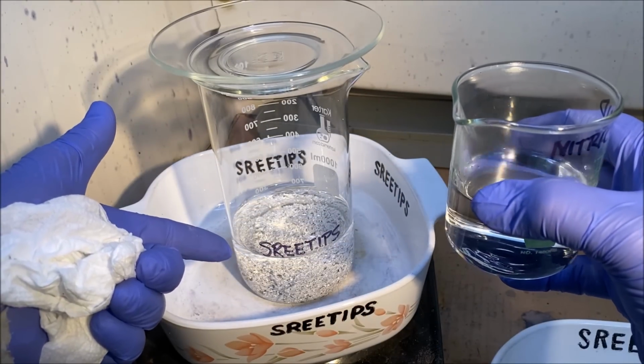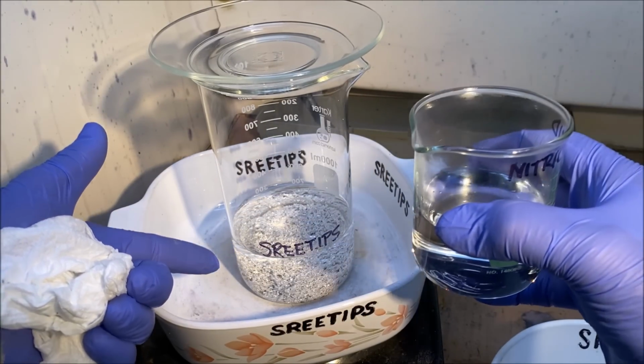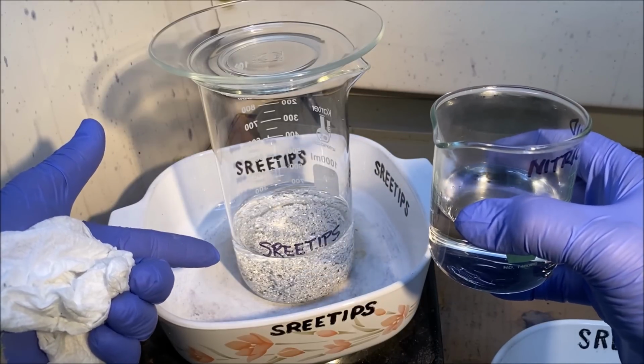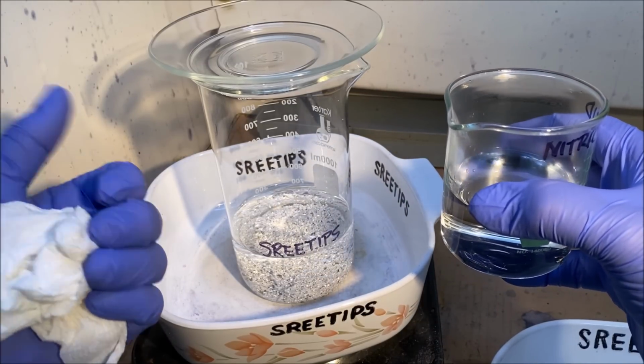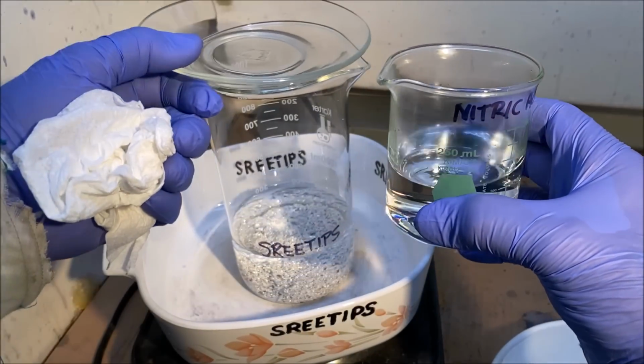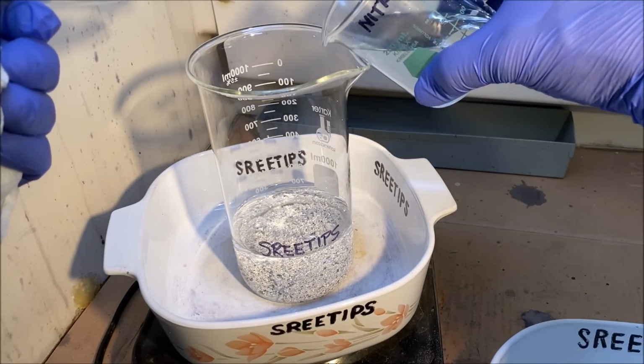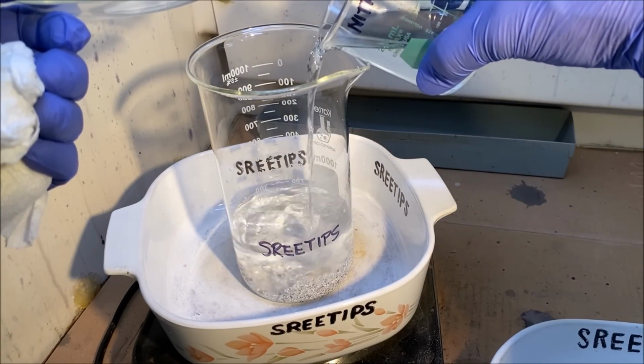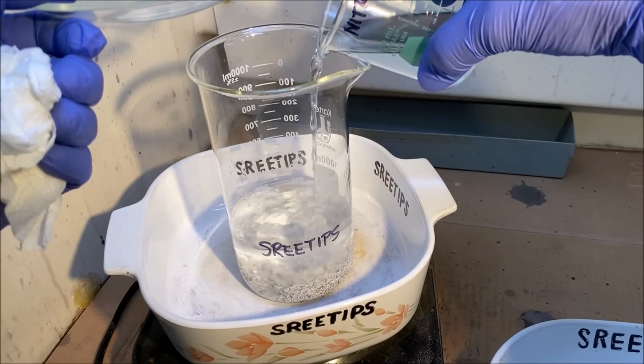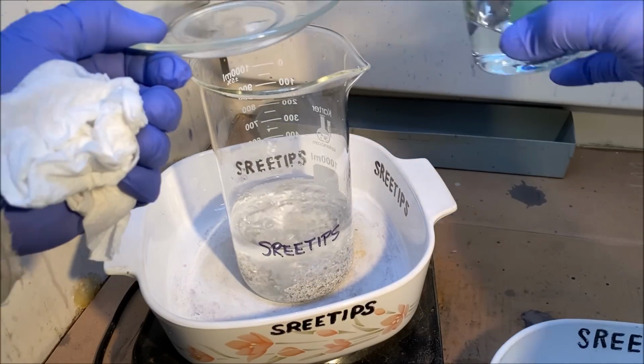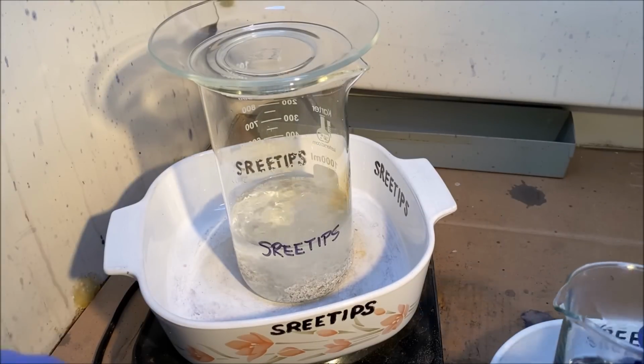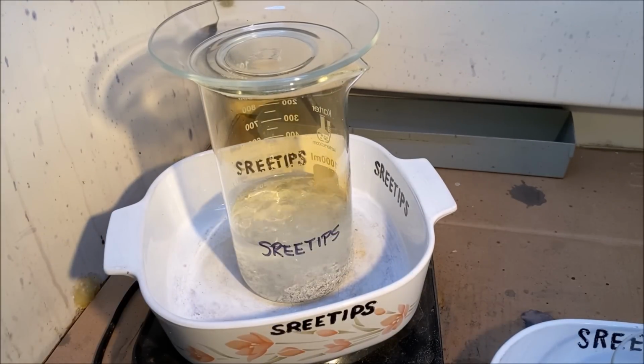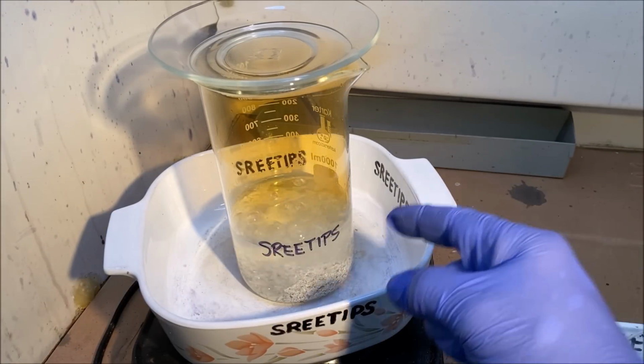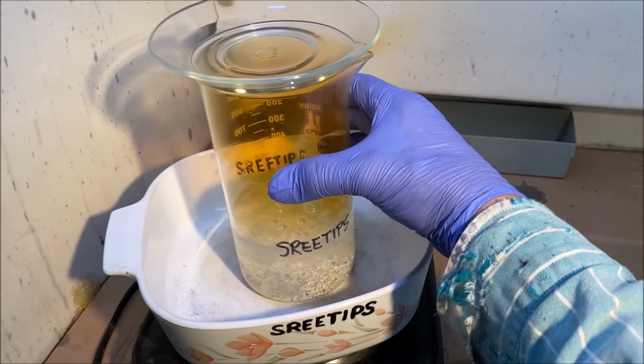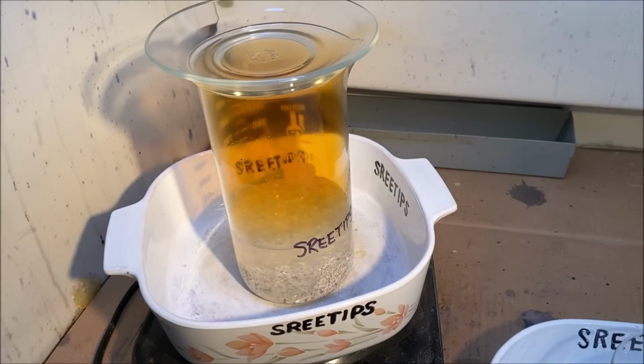We're going to dissolve this pure silver crystal and use it to augment the second run that we've got going over there of the impure silver. So I'm going to add a little bit of this nitric acid in here now. And this is kind of an experiment, if you will, to see if we get that yellow color out of the electrolyte now that we've run the pure silver crystal back through the silver cell a second time.